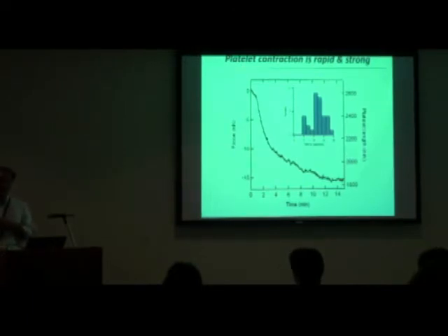So there's no variability that you know of in what you're measuring there in terms of the adhesion between the two surfaces. So that's kind of a fixed thing. Well, it's going to depend a lot on the concentration of the fibrinogen at the surface, or sorry, not the fibrinogen, the polymer at the surface. If that coating is non-uniform, that could affect the overall adhesion. But the individual adhesion strength has been measured, not in our experiments but in other experiments, and it's the number of receptors times that receptor-ligand adhesion strength is always much greater than the contraction force.